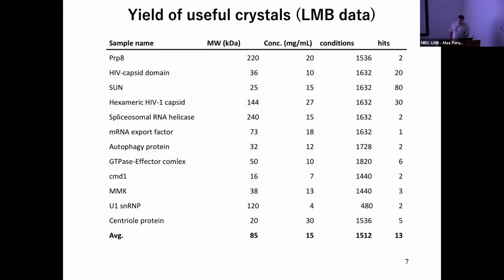A way to alter many variables at once is to screen the sample to be crystallized against a relatively large number of crystallization conditions that are formulated with a broad variety of reagents, such as precipitating agents, buffers, and many more. That's how we proceed at the LMB, our main strategy for initial screening. Here are examples when useful crystals were obtained during initial crystallization screening at the LMB against hundreds of conditions. The corresponding yield is a bit less than 1%. Considering other cases where no useful crystals are obtained, our overall yield working with novel samples is estimated to be far below 1%.